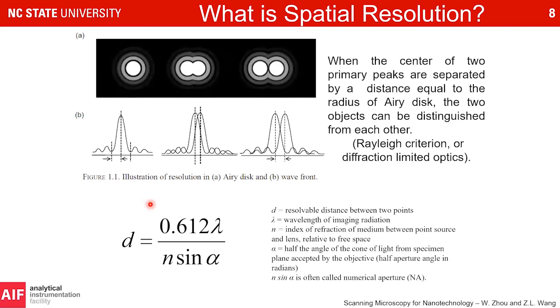For diffraction-limited optics — ignoring aberrations and other incoherent sources — the resolution d is related to the wavelength of our imaging system and something called the numerical aperture, roughly the angles allowed to enter our objective lens. The smaller we make our wavelength, the smaller the distance between two points we can resolve. This is a simple explanation for why we move from photons to electrons: the wavelength of electrons is incredibly small, giving much finer resolution.